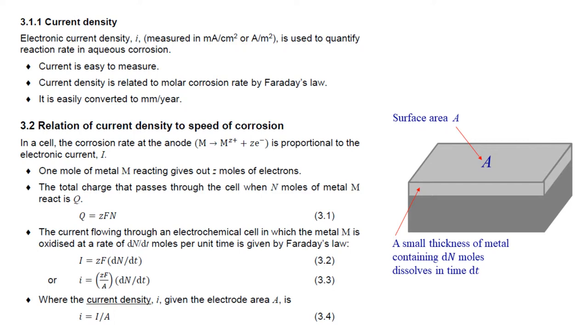In this section 3.2, we imagine this picture. We have a block of dissolving metal M, and we write down how the rate at which the metal anode dissolves into metal ions with charge Z+ is related to the net electronic current in amps, which is written in algebra as capital I. One mole of metal M reacts and dissolves, and it gives out Z moles of electrons with a total charge ZF. So, if the net charge is Q, Q describes the amount of charge passing through an electrochemical cell when N moles of this metal dissolve. Clearly, equation 3.1 is true when it says that the charge is the number of moles of metal which dissolve times the charge released per mole of metal, or Q is equal to ZFN.